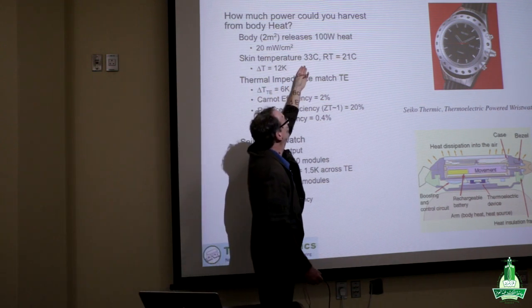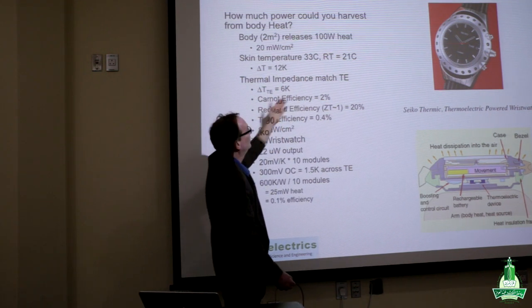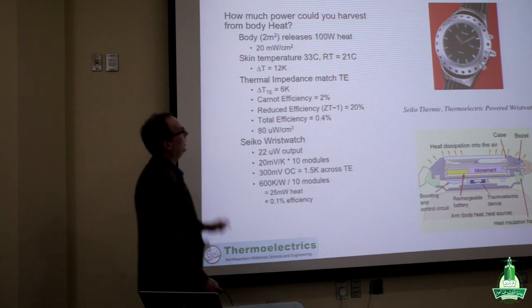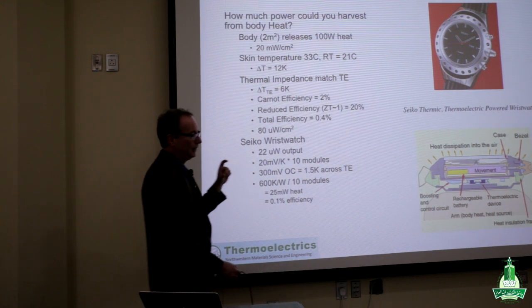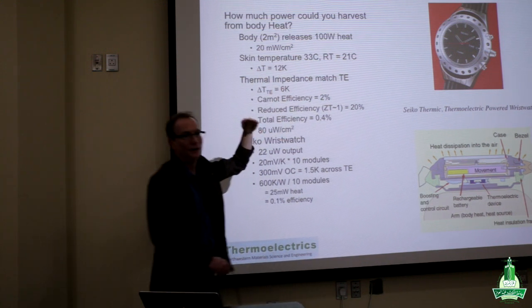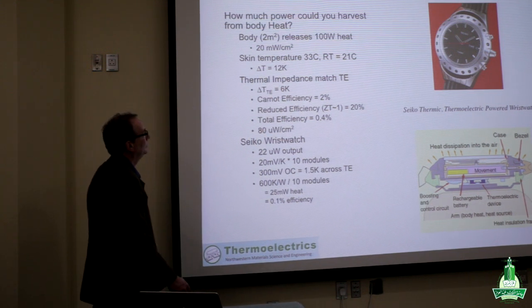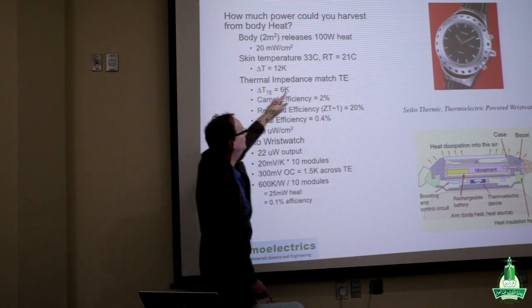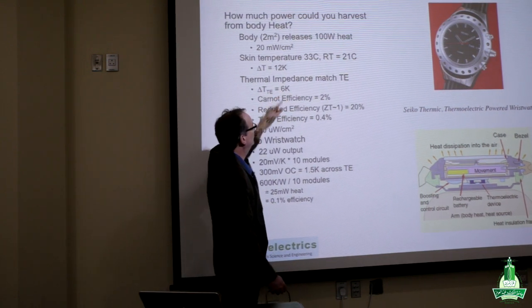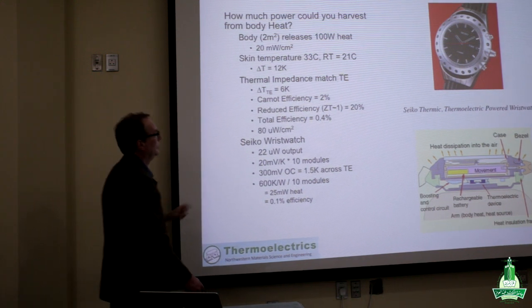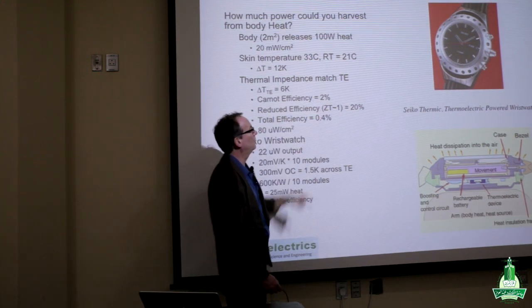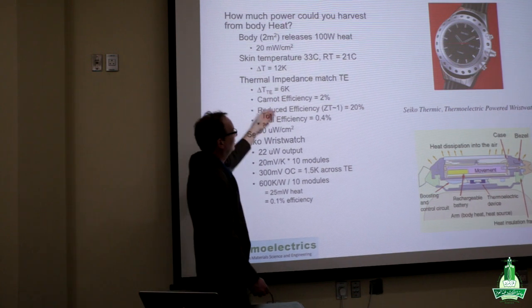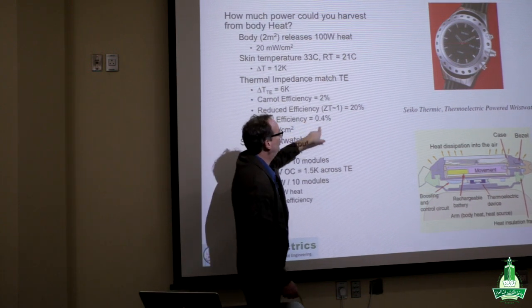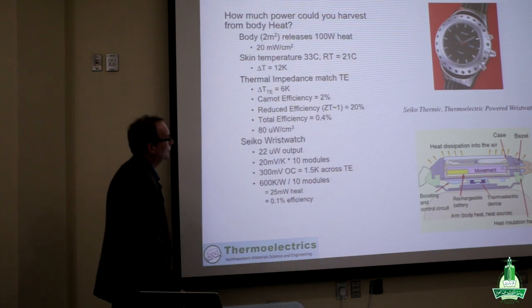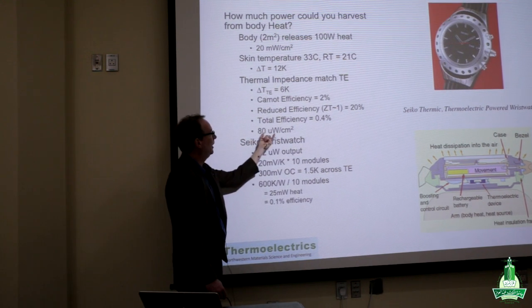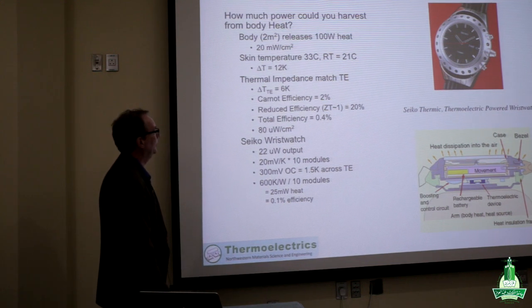For a skin temperature of 33 degrees Celsius and room temperature of 21, that's a 12 Kelvin temperature difference between the hot side and the cold side ambient, which means that under thermal impedance match, we would only get at most 6 Kelvin across our thermoelectric, which means the Carnot efficiency is already 2%. If we have our reduced efficiency of 20%, that means the total efficiency we should really ever expect is no more than 0.4%, or about 80 microwatts per square centimeter.